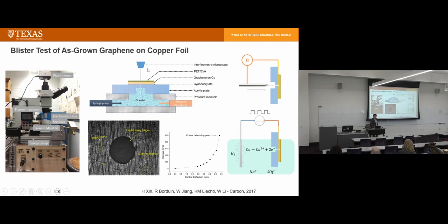Basically, you have an interferometer microscope looking at the top of the sample. So we made a PET/EVA graphene on copper sample. It turns out this sample is very hard to make because it's not transferred. We have to drill a hole through underneath and then supply pressure on it so you can see the blister forming. You measure the height of the blister to back-calculate the adhesive energy.